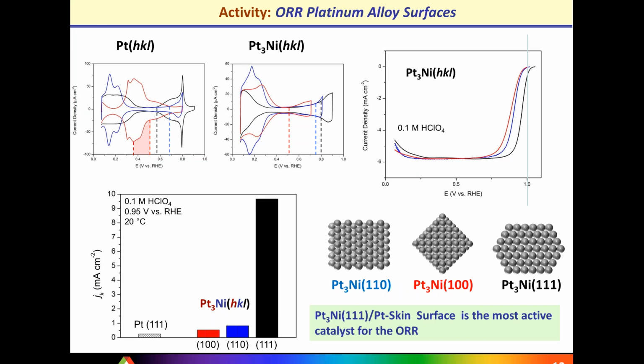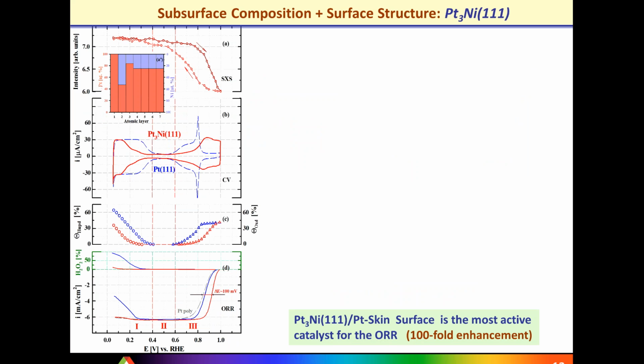So that's the reason why I'm bringing only this platinum 111 skin versus the corresponding platinum 111 single crystal, and the difference between those geometrically the same surfaces with exactly the same arrangement of platinum surface atoms. However, different bulk composition is tremendous if you compare just cyclic voltammograms, and we can see suppression of hydrogen UPD by a factor of 2. Not only was hydrogen UPD suppressed, but also the onset of surface oxides is shifted by over 100 millivolts. And all of that is followed by a substantial boost in catalytic activity which was observed.